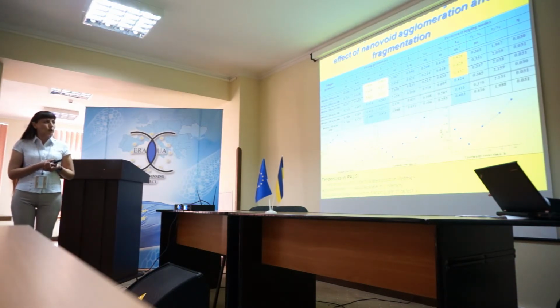So our results. In this case, we can see results for the germanium, gallium, selenium system analyzed at different times. We can see that in the initial stage of the process, the lifetime tau2 increases and intensity I2 decreases. Positron trapping rate in defects also increases.